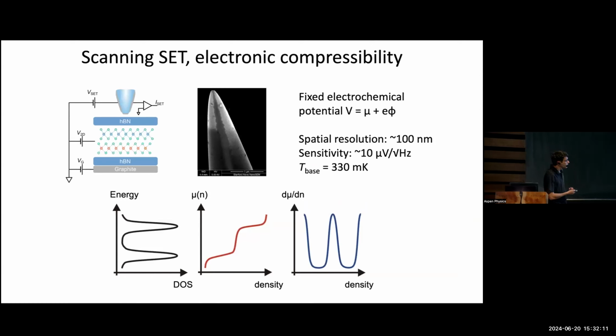How do we do it? Well, we evaporate aluminum onto a pulled quartz fiber. So this is an SEM image of what we do. We put this tip, which has the SET, the single electron transistor, right at the apex of the quartz rod. We bring it close to the sample that we'd like to study. In this case, the sample itself is providing the gating along this x-axis that I was showing you before.